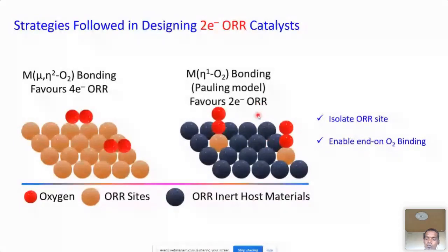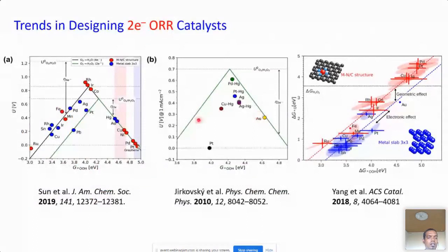So this is the strategy followed in 2-electron ORR catalyst design, and people have done so many works. Just like for ORR, we have volcano plots for 2-electron oxygen reduction reaction due to electronic effects, and people have also achieved selectivity just by following the strategy of isolation with an inert host material. Here you can see various metals alloyed with Hg, in which Hg is the ORR inert host material, and copper, platinum, Ag are the ORR catalytic sites, and they predict that it can be achieved.